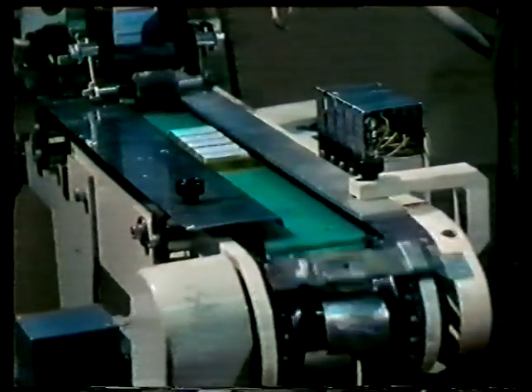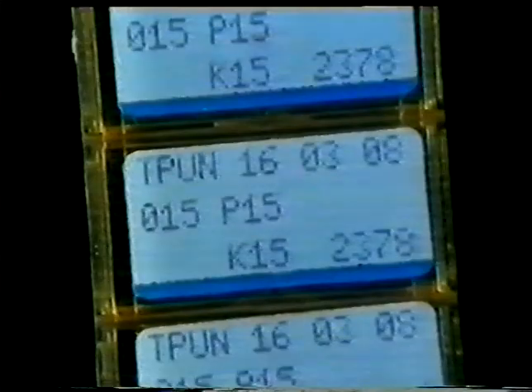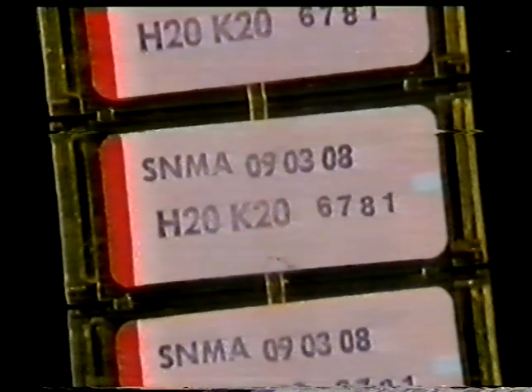The finished inserts are then packed, and the boxes are given an international color coding according to the grade of the insert. Those used for machining steel are colored blue and lettered P. These will cut steel with maximum efficiency as their structure provides high resistance to thermal cracking and plastic deformation. Inserts used for machining cast iron and non-ferrous metals such as cast brasses or those metals which form short chips are coded red and given the letter K. These are ideally used at relatively high cutting speeds with low feeds.